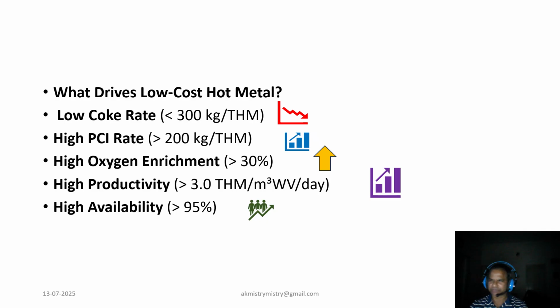We start with a coke rate under 300 kilograms per ton of hot metal and push PCI level above 200 kg per ton hot metal. With oxygen enrichment beyond 30%, these fuel optimizations drive down the cost. To keep pace, we need productivity exceeding 3 ton per cubic meter daily and availability over 95%, forming the backbone of cost effective furnace operation.